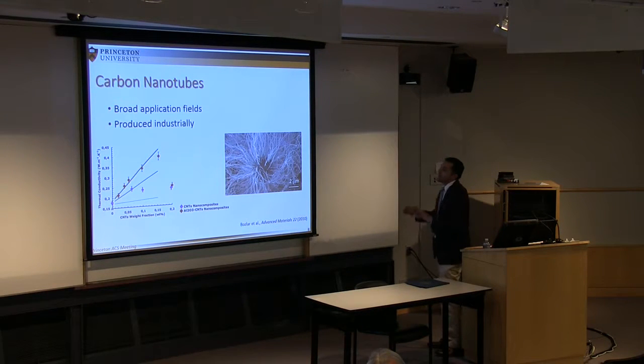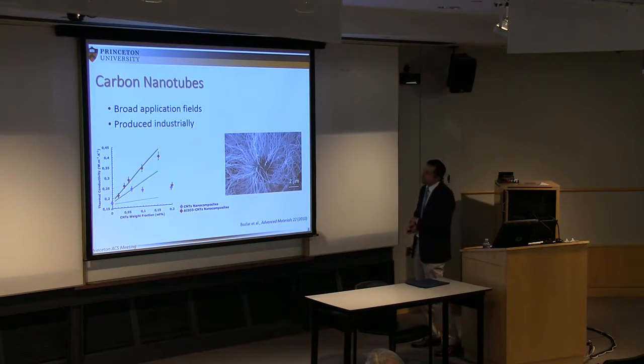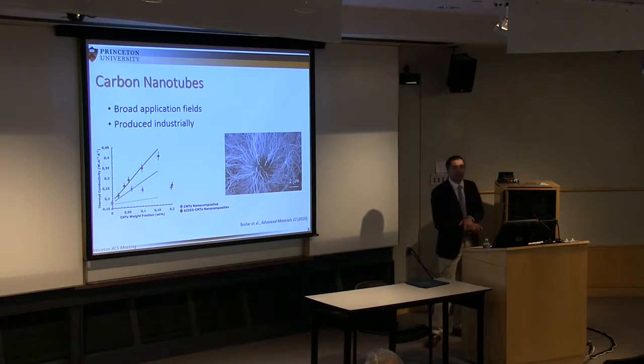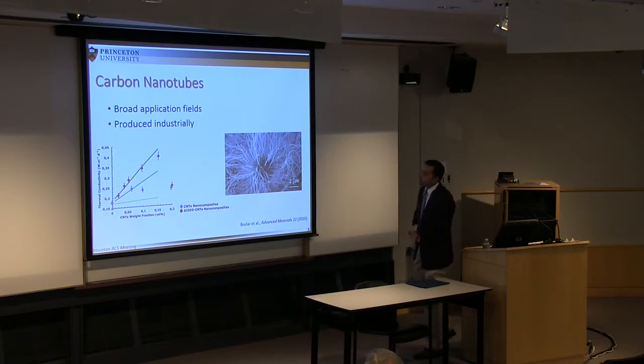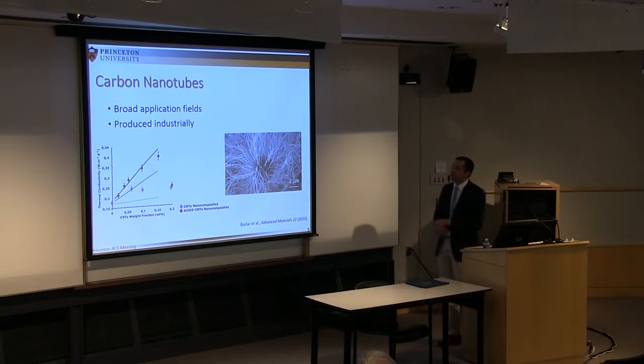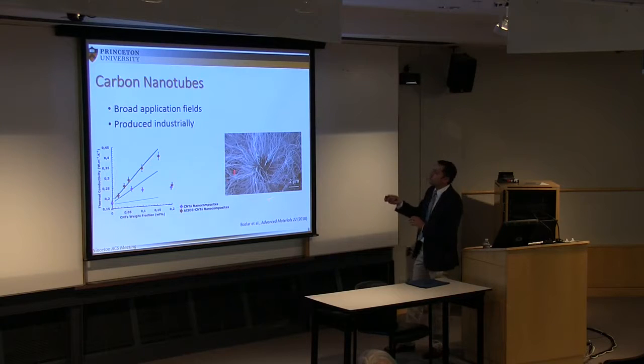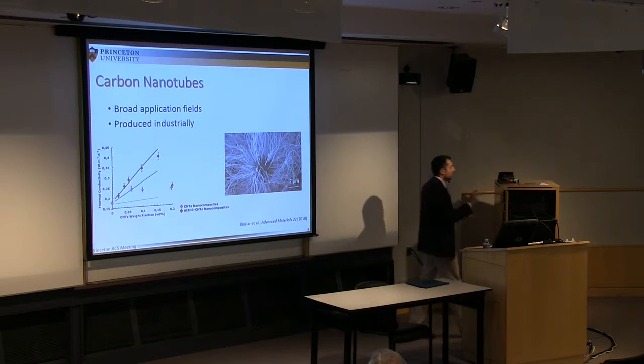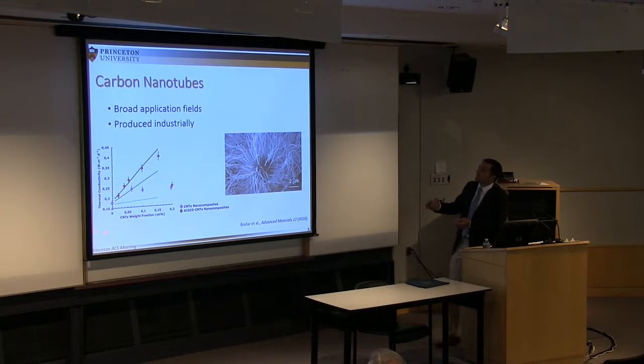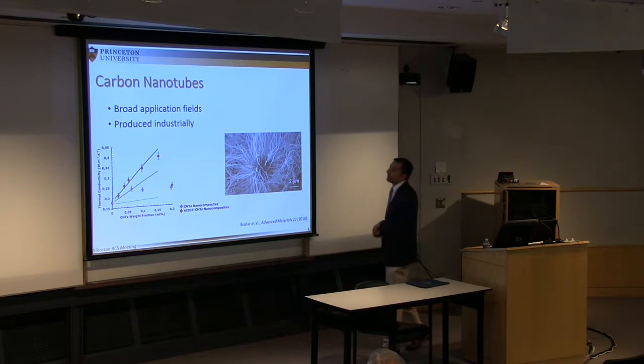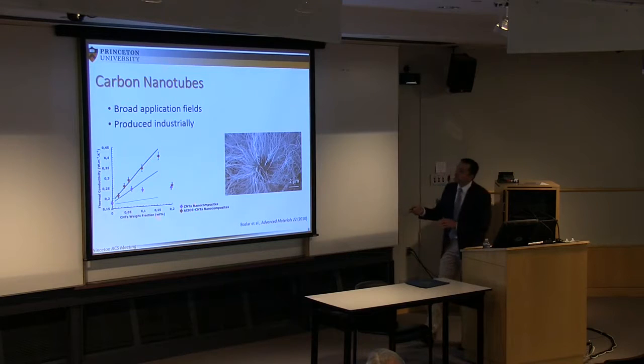And as you can see on the plot here, where we show the thermal conductivity as a function of carbon nanotube weight fraction, if you don't use the alumina particle, you see we reach somehow good conductivity, better than the polymer alone, but you don't really see a huge increase in the thermal conductivity. Whereas if you use this type of configuration, combining a micro and nano structure, you see immediately a sudden jump in the conductivity. So this is quite a significant result, 0.4 watt per meter Kelvin at only 0.15 weight %.